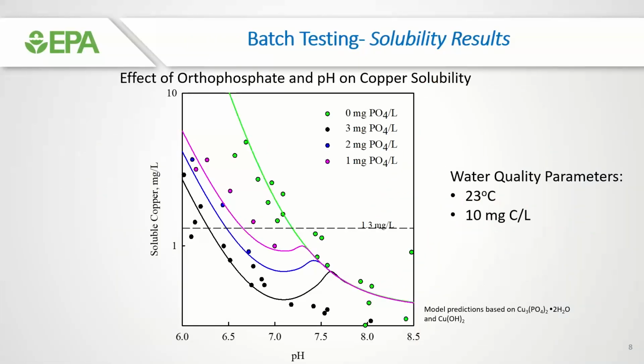Well, orthophosphate's an option. And once again, as I said, the nice thing about copper is it's fairly well predictable. So we can look at and do work showing that, if we take, for example, this particular control situation, a DOC of 10 in the green here, and add increasing concentrations of orthophosphate from 1, 2 to 3 milligrams per liter, we find that we can lower the copper concentrations at pretty much all pHs that we look at.